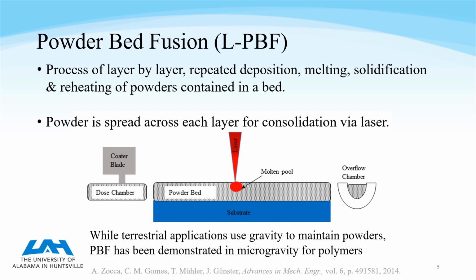The first one is laser powder bed fusion, or LPBF. In this process, you deposit a whole layer of powder in the powder bed. Then you come back with a laser and you melt the shape of your part. Then you let that whole layer cool, and then you deposit a new layer. So it's cyclical in this way. And on Earth, we normally rely on gravity to hold the powder in place as we're doing this, but there's some proof of concept work going on that shows that this can actually work in microgravity, which means that powder bed fusion is viable in space.